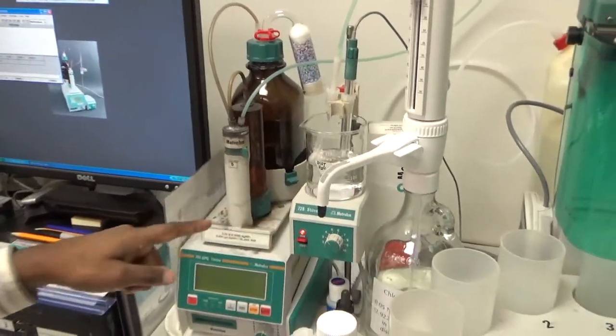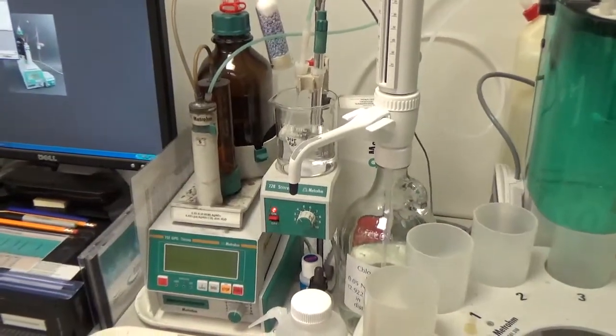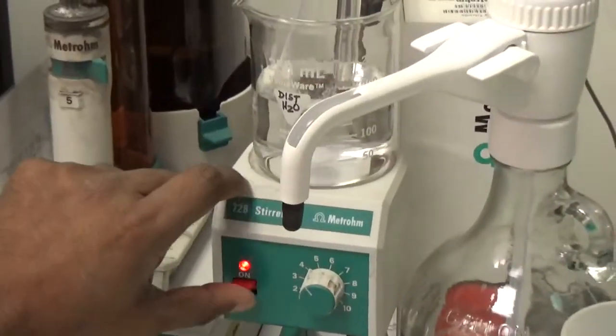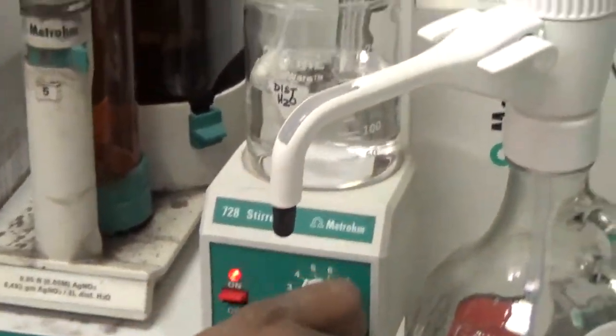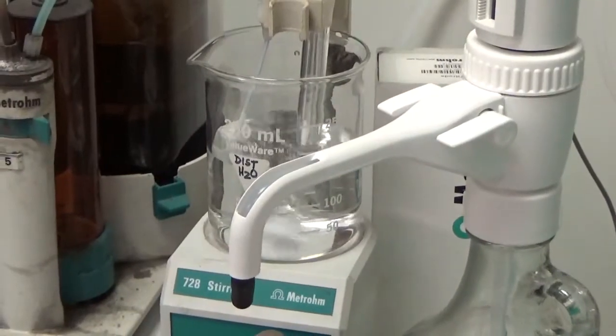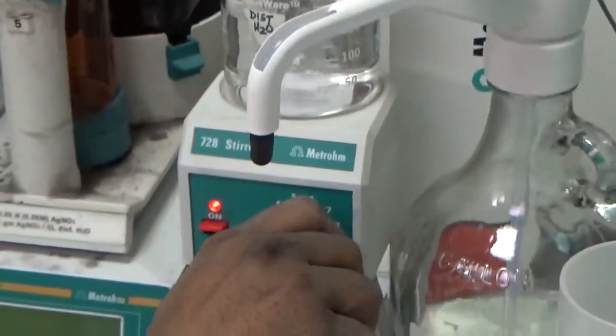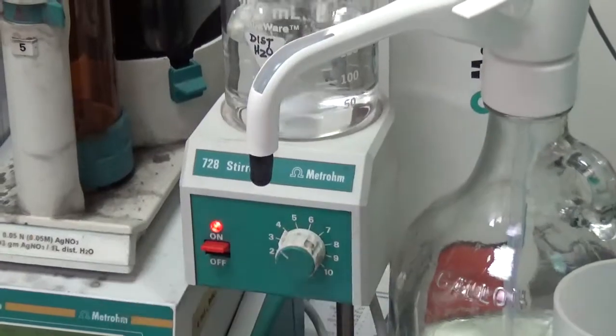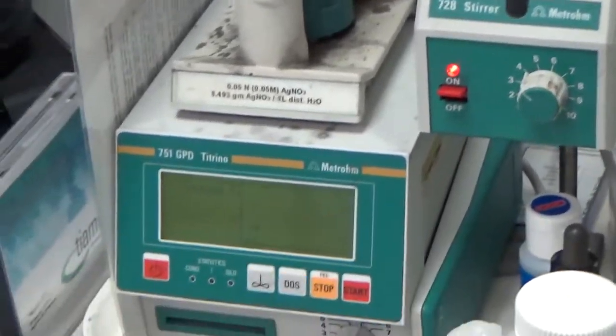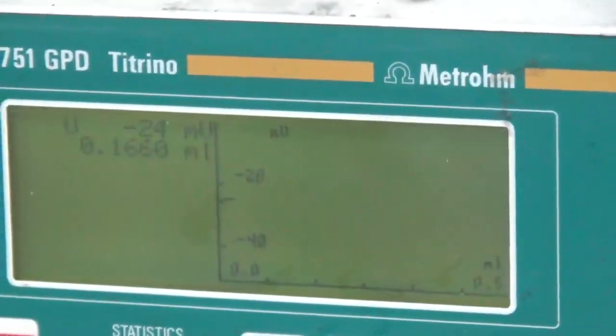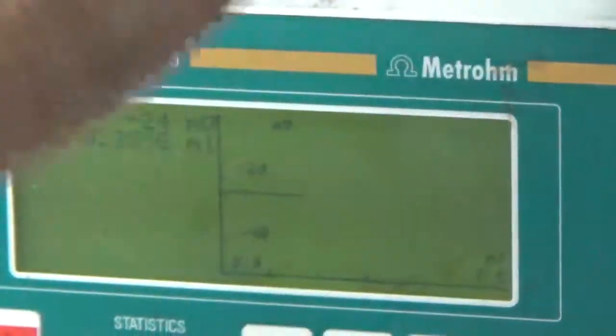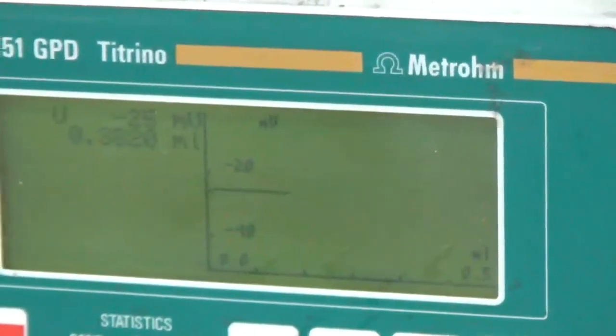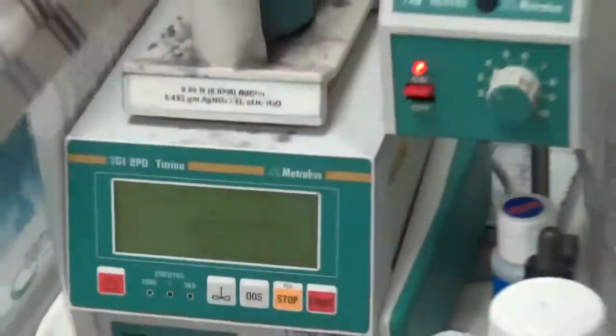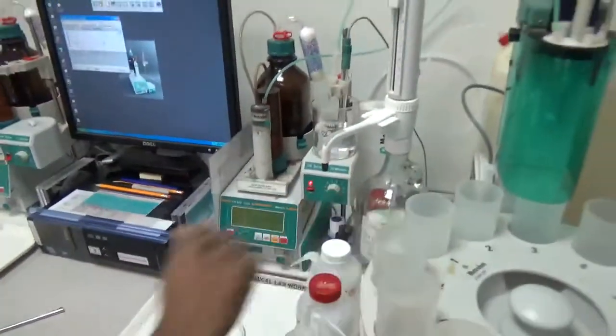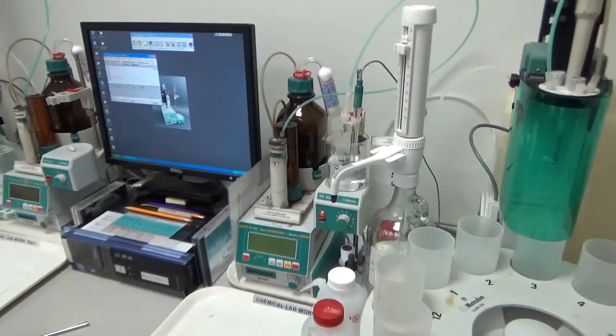Once we start the titration, the stirrer starts, the stirrer bar starts. You can control the speed of the stirrer with this knob. We stay somewhere in the middle speed. And the same way the titration starts for just one sample. So that's why we can use the 728 stirrer to do small volume titration, or we can use the 722 stirrer for multiple samples in the automated titration.